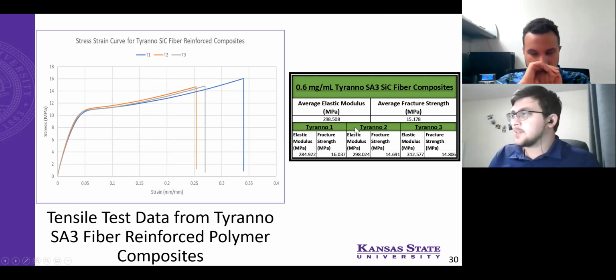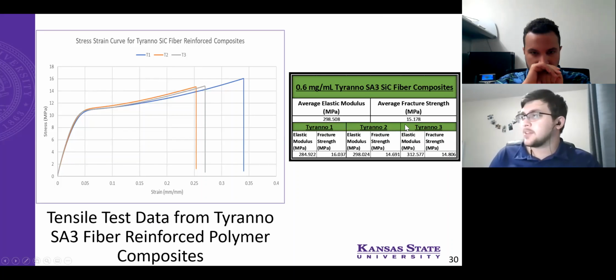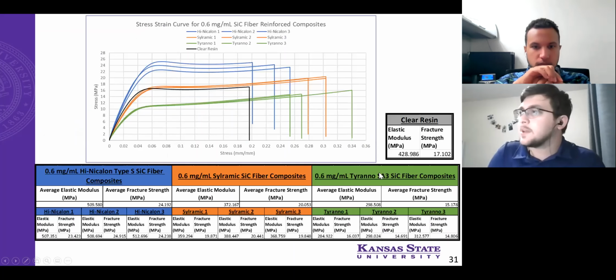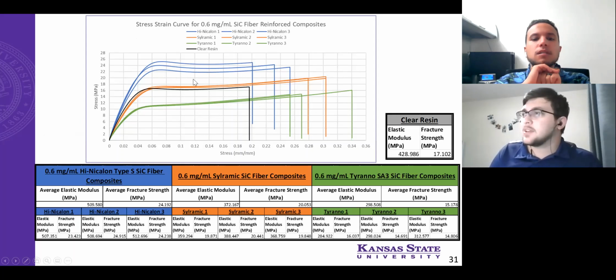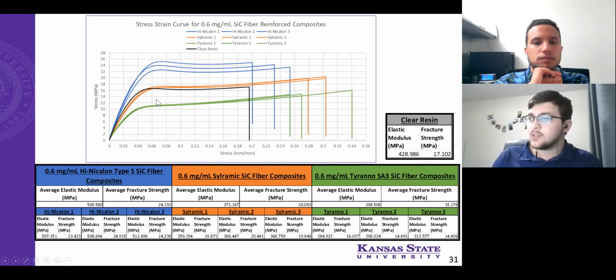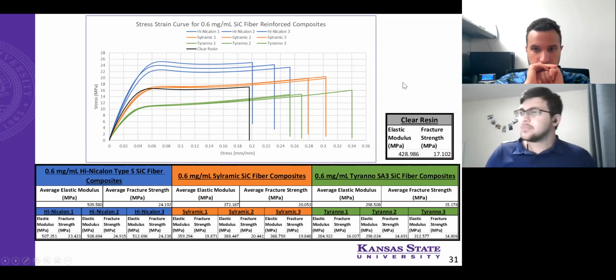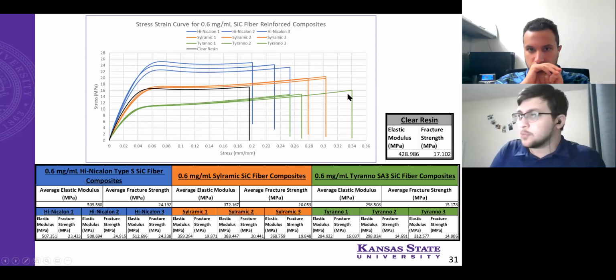At 300 megapascals and 15 megapascals fracture strength. We'll just jump ahead to the comparison here. Here you can see the Hi-Nicalon, again, just really performing better than the other two fibers. And the ceramic outperformed the neat resin in terms of fracture strength, but was slightly less in the elastic modulus with the 430 versus 372 megapascals. And then again, the Tyranno did underperform compared to the other two, which again may be due to that